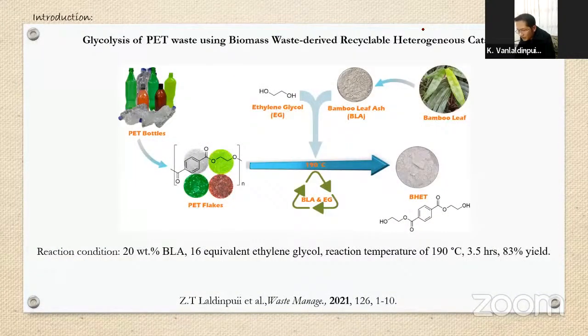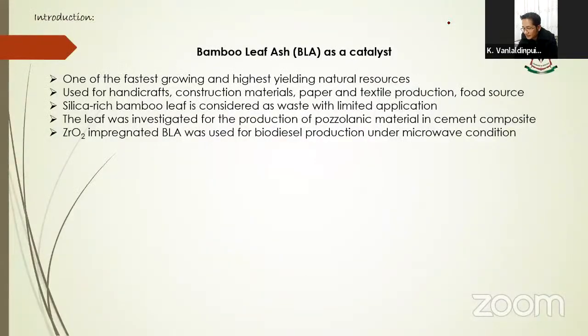Then we also investigated bamboo leaf ash as a catalyst. Bamboo leaves were collected and, as before, washed thoroughly with distilled water. And we follow the same protocol and collect the ash. So the ashes were collected, ground to a fine powder, and sieved. The reaction was carried out with 20% of BLA, with 16 equivalent of ethylene glycol at a reaction temperature of 190 degrees Celsius. And the reaction takes 3.5 hours, giving 83% BHET yield. So bamboo is one of the fastest growing and highest yielding natural resources, we know that. And this is the reason why we chose it.